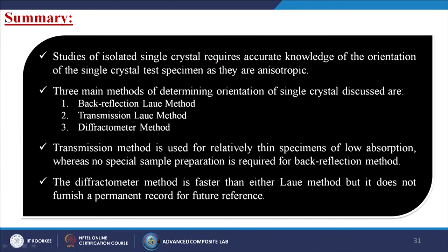The transmission method is used for relatively thin specimens of low absorption, whereas no special sample preparation is required for the back reflection method. The diffractometer method is faster than either Laue method, but it does not furnish a permanent record for future reference.